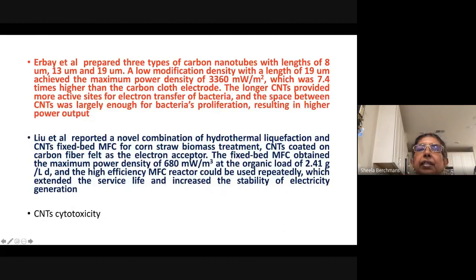There are other reports in the literature about the use of carbon nanotubes. One group developed carbon nanotubes with 3 different lengths, 8 micrometer, 13 micrometer, and 19 micrometer. A low modification density with a length of 19 micrometer achieved a maximum power density of 3,360 milliwatt per meter square, which was 7.4 times higher than the carbon cloth electrode. The longer CNTs provided more active sites for electron transfer of bacteria, and the space between CNTs was large enough for the bacteria's proliferation, resulting in higher power output.